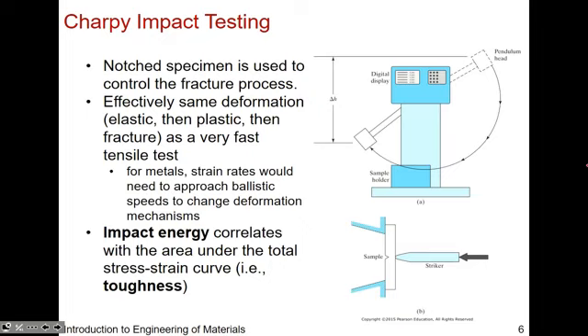If you just machine something, you want to see what kind of impact, what kind of toughness it has. The impact energy that it can absorb, you do these very standard materials and mechanical engineering tests called the Charpy impact test. So you lift the weight and then you drop it, and based on the mgh difference, the difference in height of how much this pendulum swings, you can back calculate how much energy has been absorbed, right? So you could talk about a material's toughness that way as well.